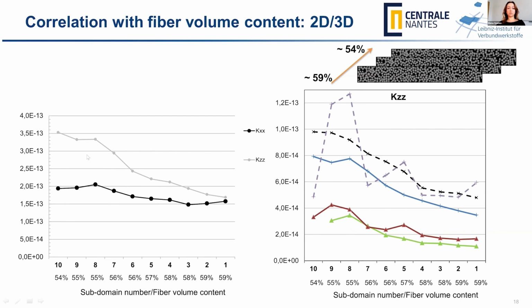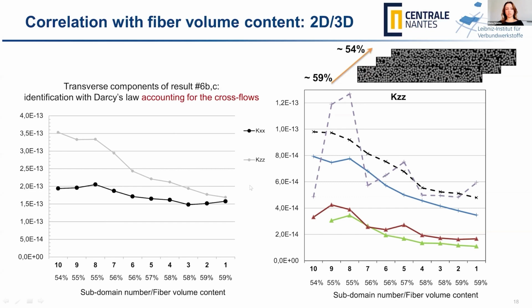And this decreasing result was because the calculation technique calculated the full permeability tensor. That's what we found out actually. When we wanted to retrieve this trend, really the homogenization technique or volume averaging had to be used to calculate the full permeability tensor.